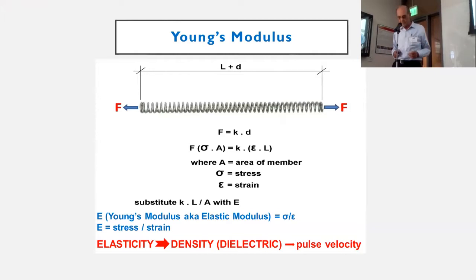The most important thing I want to leave you with at the end of today, if I can, is that most of what we are doing is density related. With all these tools, we are looking to compare a certain density to another. And that's what establishes what we're looking at. For example, the density of concrete, which is what we're looking through when we're using GPR, is around 150 pounds per cubic foot. The density of steel, which is what we're trying to establish whether it's there or not, is about three and a half times that.